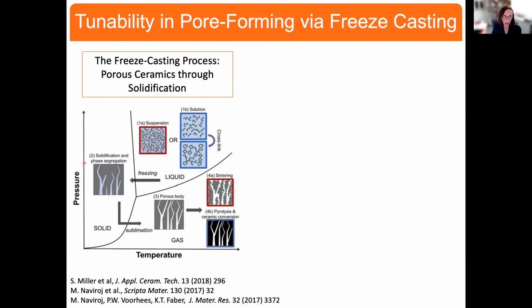And what I show here in this pressure temperature diagram is really a map which describes the solidification process. So we can do this in one of two ways. We can start with a suspension of powders in some sort of dispersing fluid. It can be as simple as water. We have also concentrated a lot of our effort in using pre-ceramic polymers that we put into solution, and we cross-link it. Now, this is generally done at ambient temperatures. And at that point, we then decrease the temperature in the system. And specifically, for our interest here, we do this directionally.